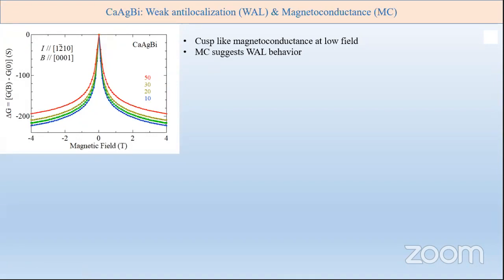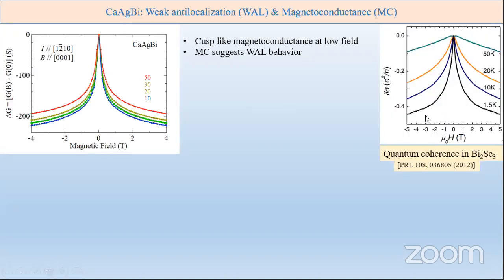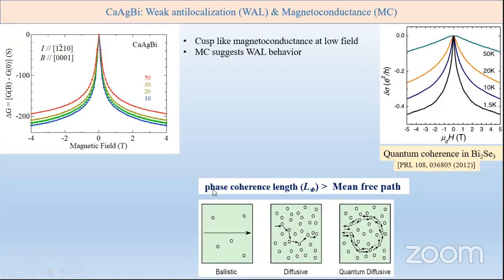At 300 Kelvin, we calculated the hole density and the electron density as well as mobility. When we measure the magnetoconductance, we have seen a cusp-like behavior at low field, and at high field it becomes almost linear. This behavior is also observed in Bi2Se3 crystal, where it has a sharp cusp-like behavior at a low magnetic field and then becomes linear. Basically, it happens when the phase coherence length is larger than the mean free path. In the diffusive region, the charge particle always gets scattered due to scattering centers. But when the phase coherence length is greater than the mean free path, even after a few scatterings, the phase coherence is preserved. In that limit, the interference happens between two channels.